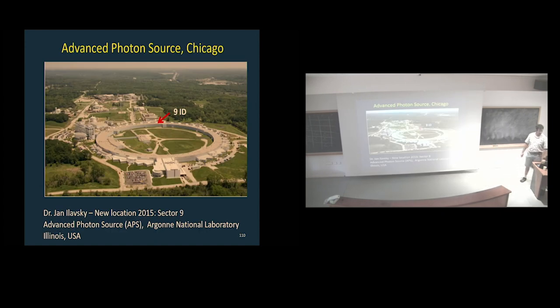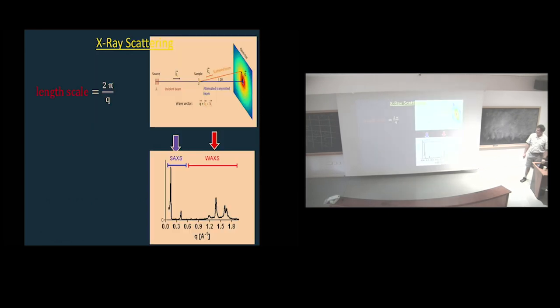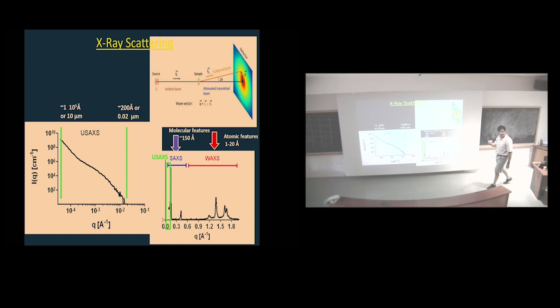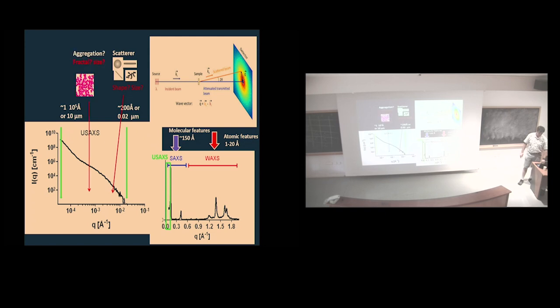So we did a lot of work in the USAXS at Argonne. We spent so much time there. You know about scattering. That's a characteristic length scale, 2 pi over q. I told you about polymorphism and the small angle region. USAXS is like where no man or woman has gone before, like over there in really small. And you get patterns like this. Now this is scattering as opposed to diffraction, and you have to make some idea of what that is. And people use it in your field because you can study big things in the micron range there.